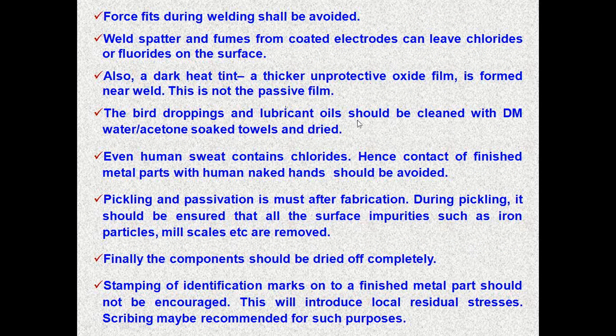Including the bird droppings and lubricant oils, these should be cleaned with DM water. Even human sweat contains chloride, so I recommend using gloves instead of naked hands to handle finished components. Pickling and passivation is a must, and after passivation you have to ensure that scales are removed. Finally, the components should be dried up totally.